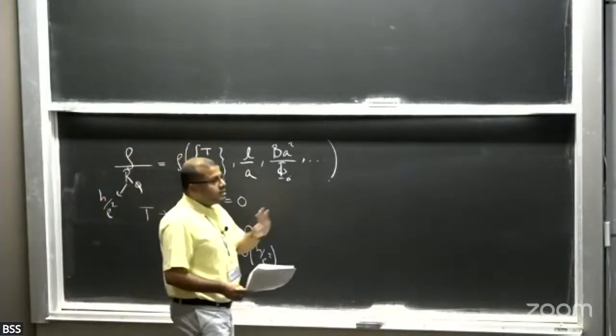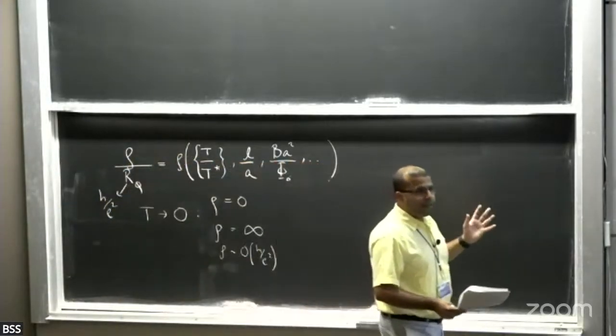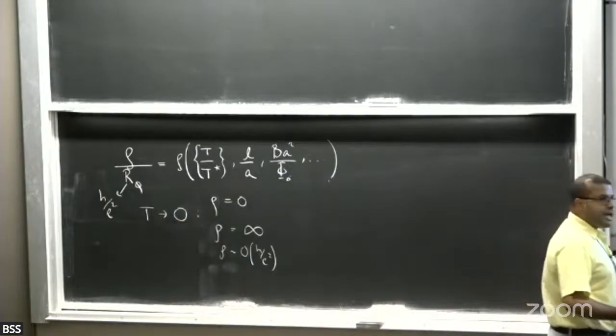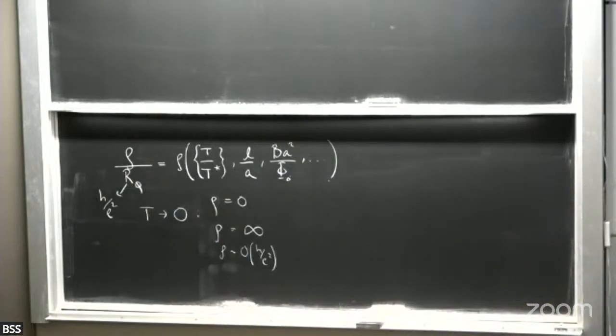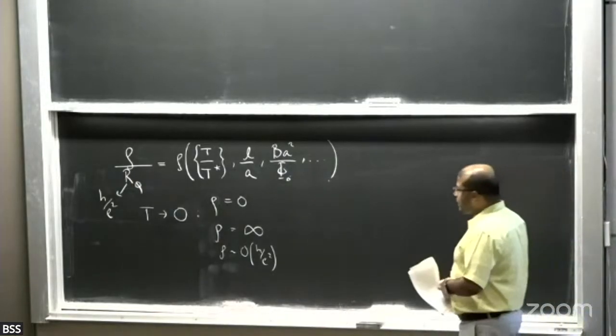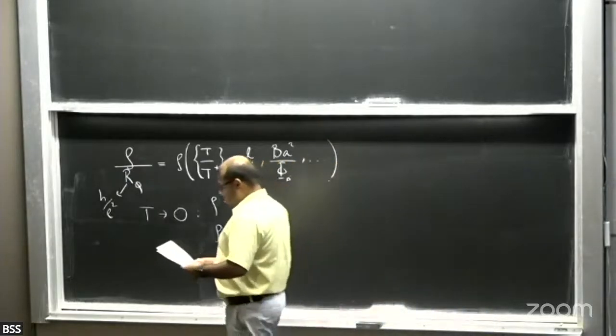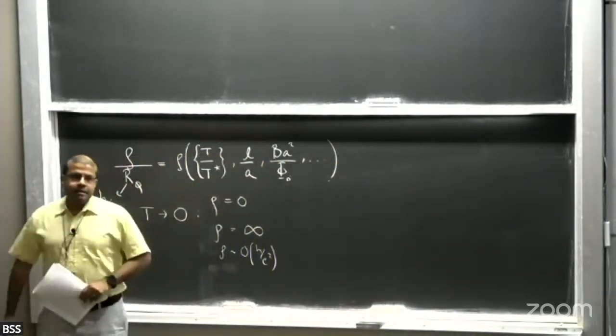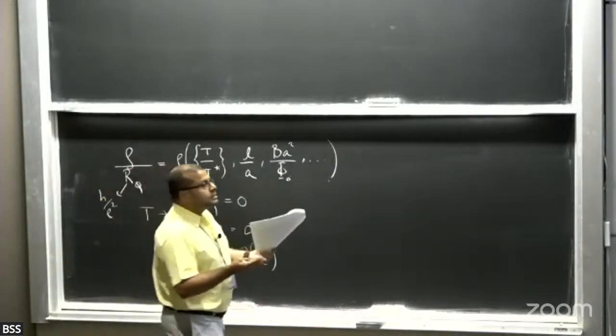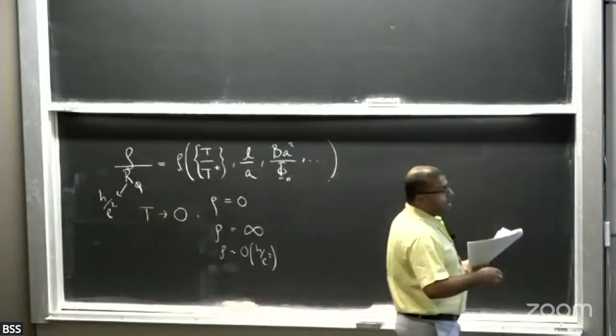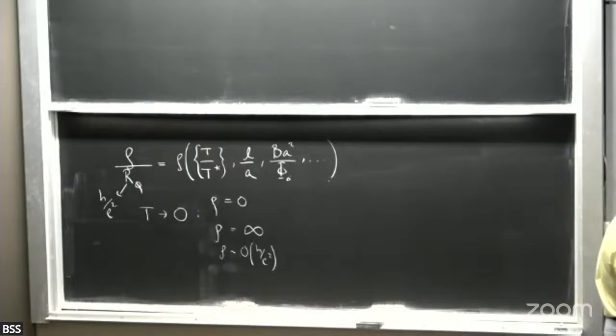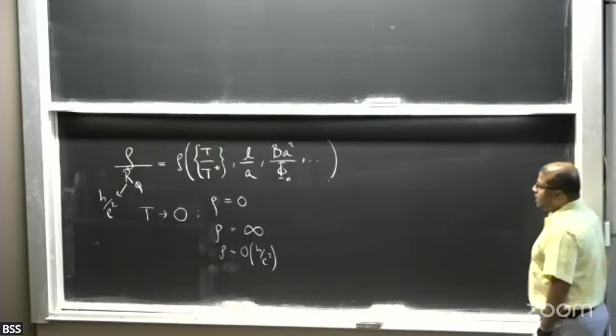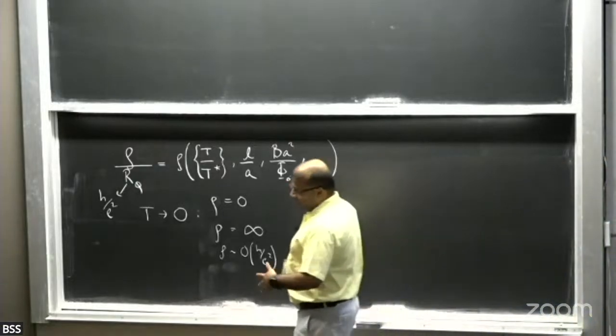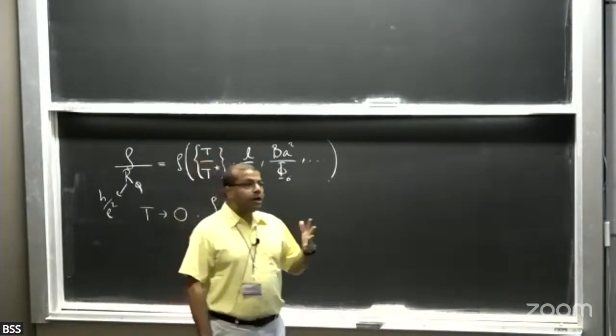If you think about most conventional metals, let's say copper or something like that, the dominant source of scattering, if you're thinking about DC resistivity, is electron-phonon scattering. I'll show you a plot of what the resistivity looks like in a second. And so then, when you see power laws, and in electronic solids, electrons are scattering off of everything, each other, disorder, phonons, maybe grain boundaries, who knows. You can get all kinds of bizarre crossovers and so on.